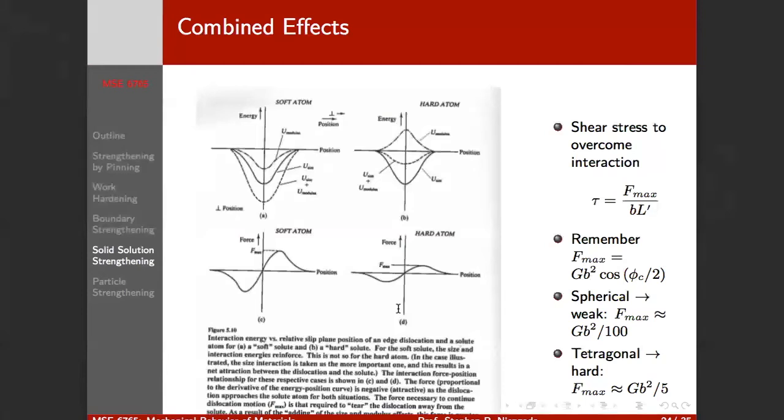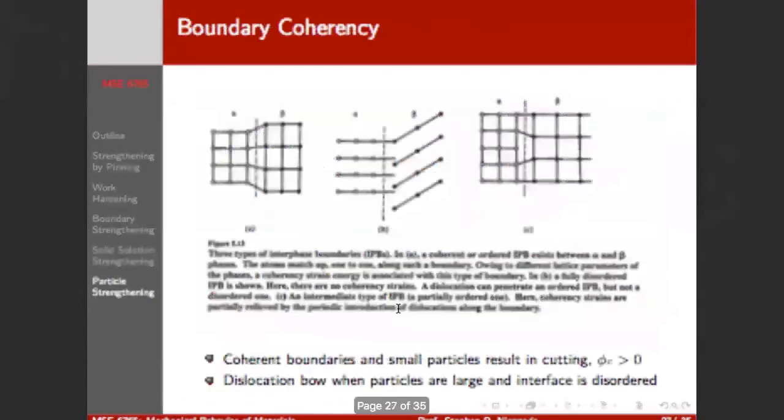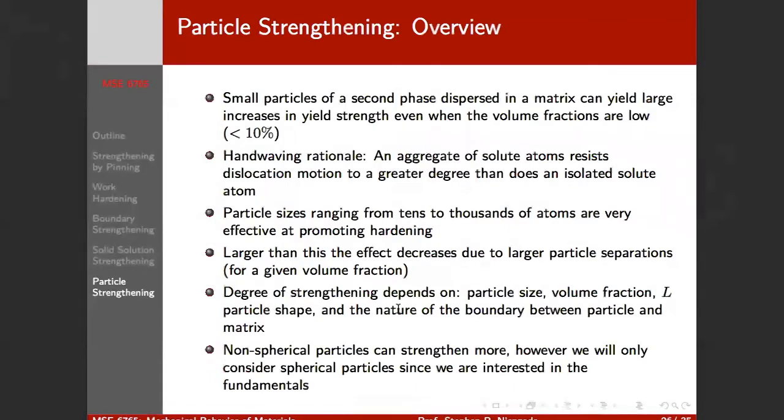So what's roughly the biggest size difference that we can get? What's from sort of our Hume-Rothery rules, right? If we get too big of a size difference, it's not going to be a single phase solid solution, right? It's going to phase separate. So what's a rule of thumb for the biggest that we can put in? 15%. About 15% size difference, right? Okay, and so that's the overview of the solid solutioning.